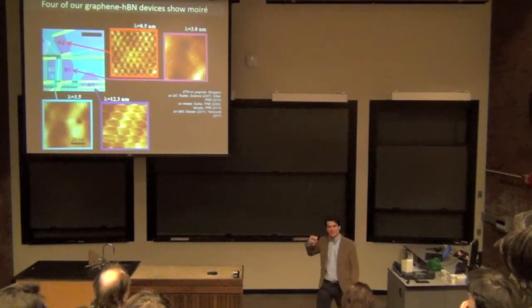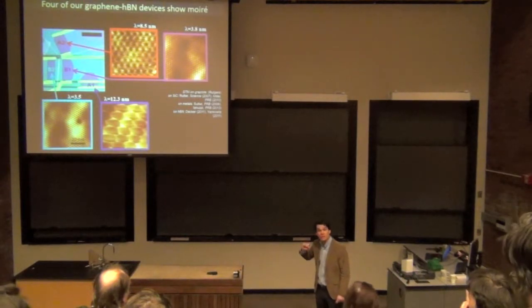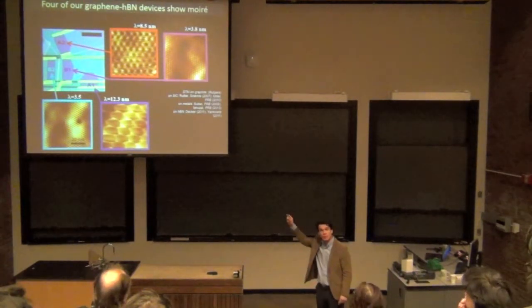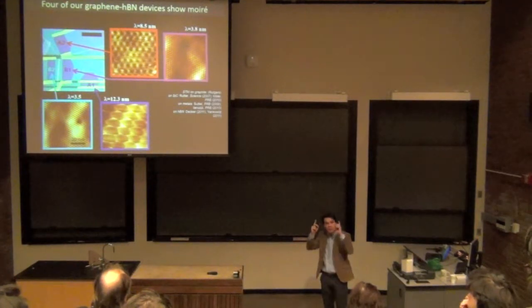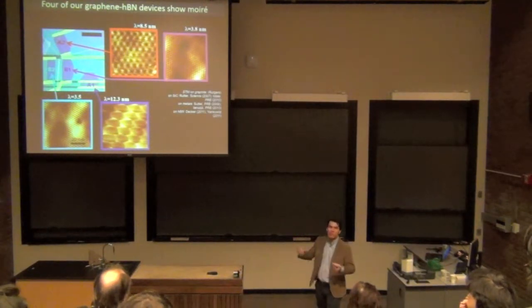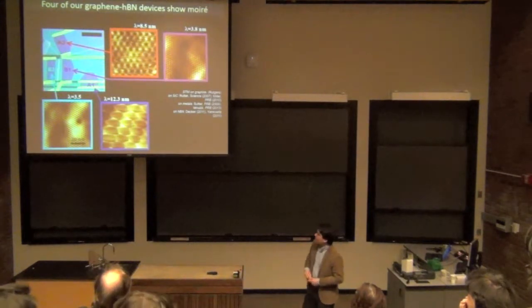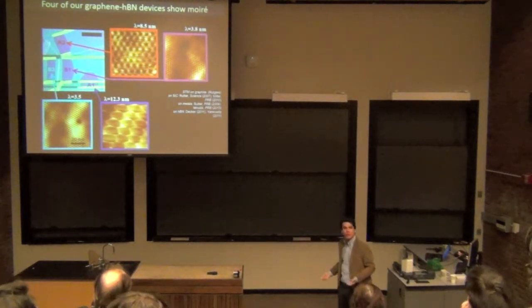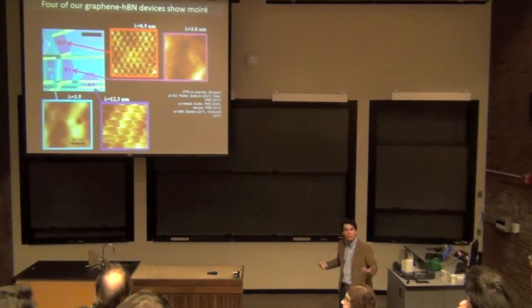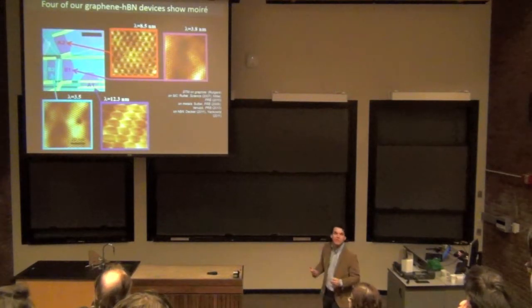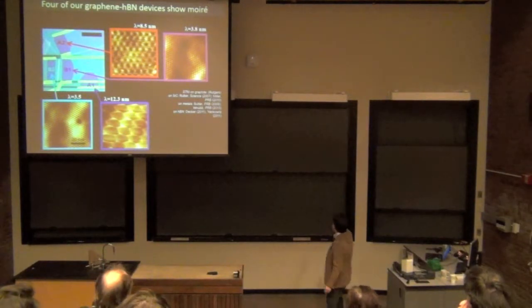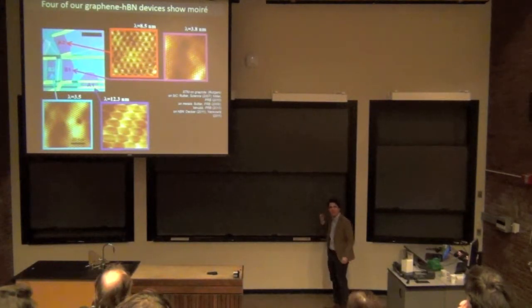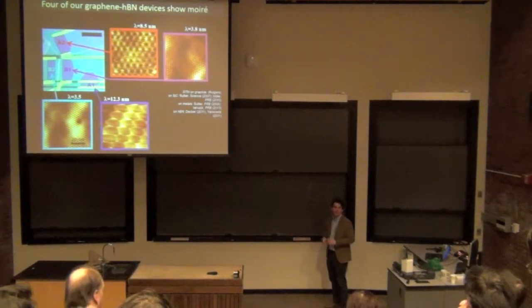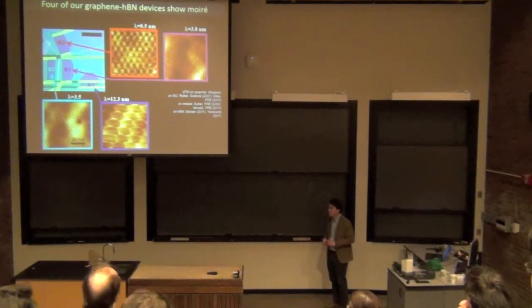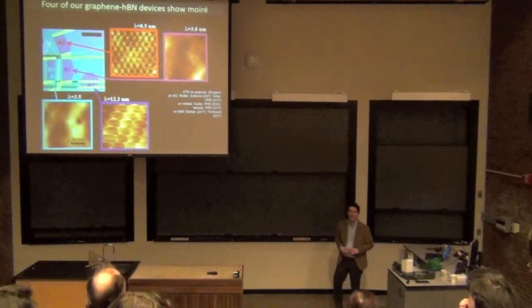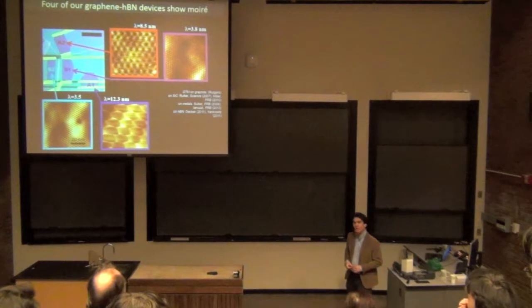These four were an accident. We were looking at the quantum spin Hall effect, and we discovered this. We discovered that we had these satellite peaks and this immense gap, or this immense insulating state. And so we've gone back and we've been able to reproduce the low twist angle physics, at least to 45 Tesla. And we did that by basically aligning these crystallographic axes. But I would say we can't do much better than about a half a degree or a quarter degree. That's the state of the art of aligning them right now.